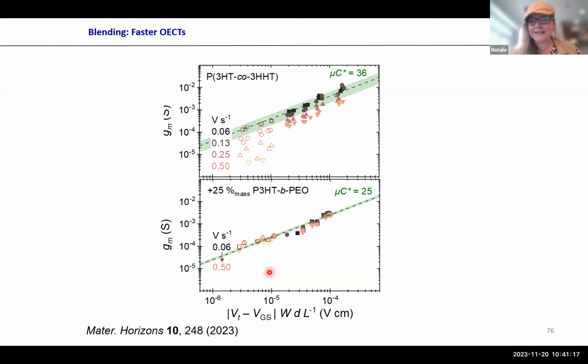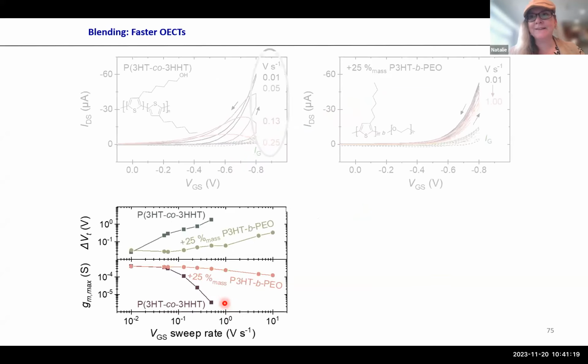Natalie? Moreover, if you do, yes? Have you done a control where you don't use the block polymer, but you just blend with PEO? Yes, we did, and I expected that question. I don't actually have the data. Only PEO itself actually also works. It's just much more difficult to get really homogeneous films. So the yield of well-behaving films is much lower.